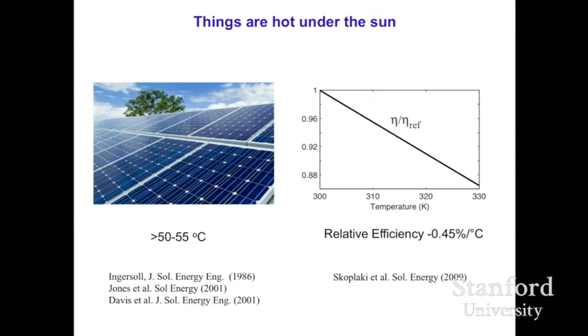So as a background, I hope I've shown you enough experimental data to convince you that a roof is a very hot place. And a solar cell, remarkably, does not really sit in an air-conditioned room under a solar simulator in somebody's lab. It actually sits on a roof. And therefore, a practical solar cell actually operates at a temperature much higher than the ambient air temperature. A typical number that people quote can be somewhere on the order of 50 to 55 Celsius.